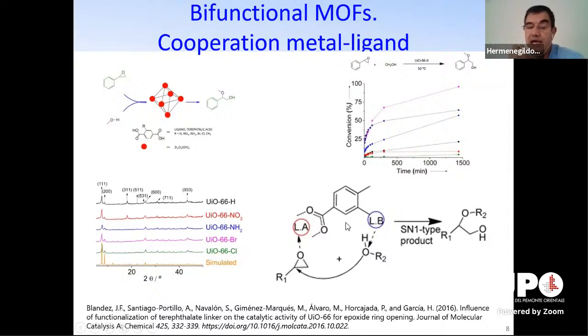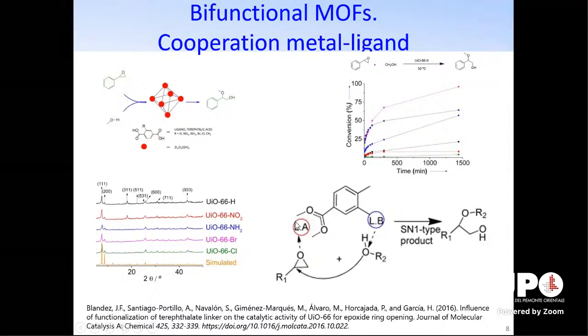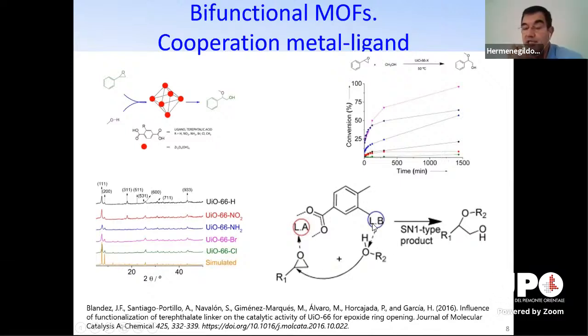And this is our proposal: when you have a basic site, like an amino, at a certain distance of the acid site, they combine because you are activating the two reagents. In the basic site, you are activating the more acidic reagent, that is the alcohol, while in the acid site, you are activating the basic reagent, that is the epoxide. And in this case, we have the product. The product occurs with a nucleophilic substitution type 1, and the reaction is much higher than if you don't have this substituent. And this is because of the cooperation between the Lewis and the basic sites in the material.